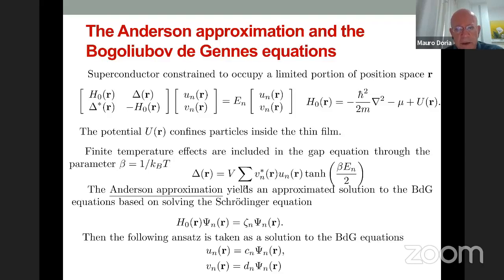How these equations work, I will not deduce them, there's no time for this, but what you have is a Hamiltonian here, H0, which is the Schrödinger Hamiltonian with a potential, and this potential will help to confine the electrons inside the film, for instance. And this is the gap. And you have to determine 2 functions, U and V, and determine their energy levels. However, this structure that you solve has to be done together with this self-consistent equation. This delta is essentially the gap. That's the attractive interaction, and you have these functions Un and Vn that feed into this delta, and then you have to solve everything together with the potential.